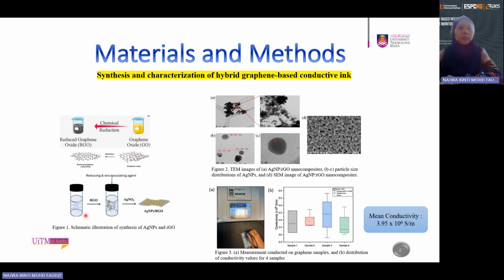A solution of 50% reduced graphene oxide and 50% silver nitrate, along with a reducing and encapsulating agent, was prepared and then incubated to facilitate the formation of silver nanoparticles and reduced graphene oxide. This is the TEM and SEM image of silver nanoparticles for the hybrid graphene-based conductive material, and it can be seen here. The silver nanoparticles exhibit a particle size distribution ranging from 10 to 25 nanometers.